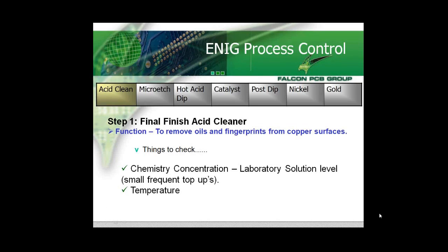We, as usual, start with an acid clean. The most important things that we use this for are to remove any sort of oils, fingerprints and any other contaminants from the copper surface. The important thing are laboratory solution checks, which we do on a regular basis. We use SPC to actually chart the results, and then what we're looking, of course, are for trends and to see whether we can improve by either extending the actual test or looking to bring in the upper and lower control limits.